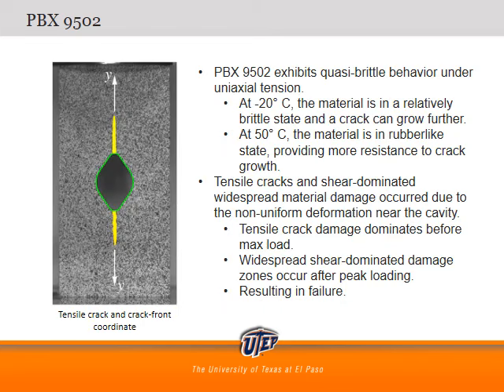It was observed that PBX 9502 exhibits quasi-brittle behavior under uniaxial tension. At negative 20 degrees Celsius, the material is in a relatively brittle state, and a crack can grow even further than it would at a higher temperature. At 50 degrees Celsius, the material is in a rubber-like state, and more resistance to crack growth is provided. Failure did still occur at 50 degrees Celsius, but it was in a much more graceful fashion than it was at the lower temperature. At negative 20 degrees Celsius, the material shattered during failure.